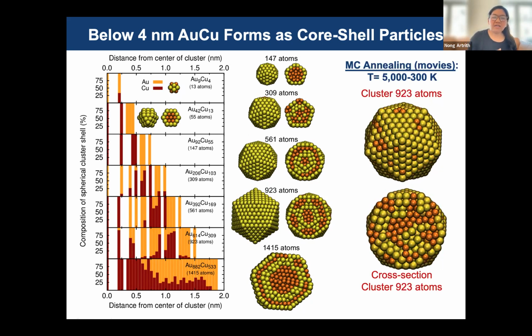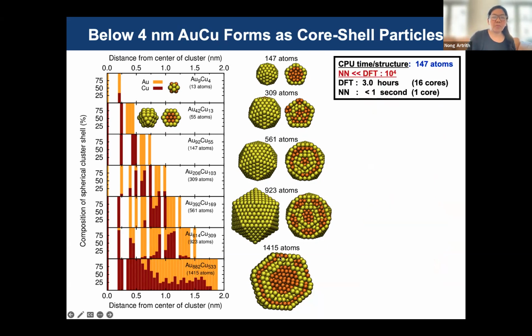We let it run and select only the structures once they reach equilibrium in different phases. Then we average the number, or the concentration, or the composition of the copper and gold in the structures, as you can see here. In the structure in vacuum, you can see that the gold, in yellow, likes to stay on the surface, and the copper likes to mix inside the nanoparticles. In the larger ones, you can also see it rearrange and mix. It's really nice, like core-shell particles.